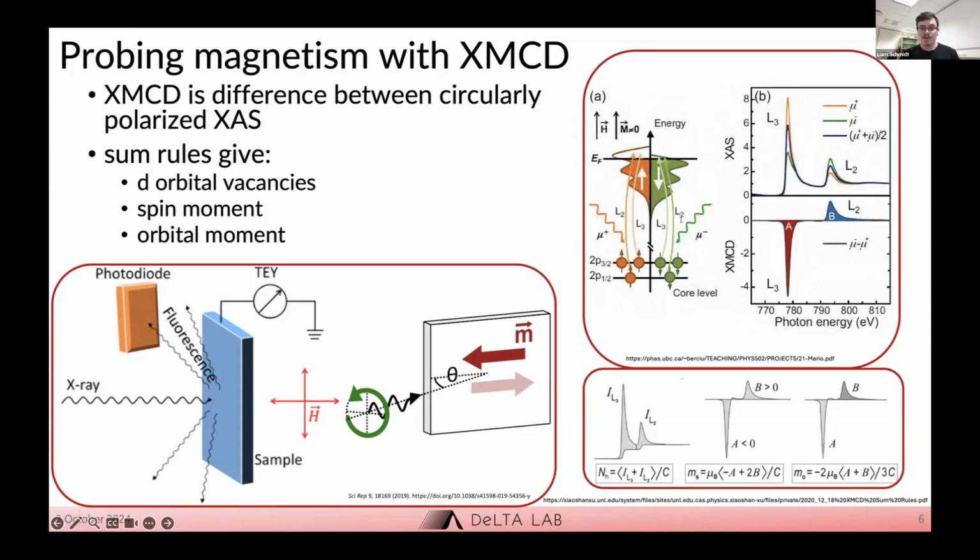So this experiment was conducted at beamline 402 of the Advanced Light Source at Berkeley. Our setup involved a 0.5 Tesla field ported along the direction of the scattered beam shown in the bottom figure here. And we report our results using total electron yield, where you measure the amount of electrons that you're ejecting from your material using a copper wire connected to a sample mount within the detector scheme.